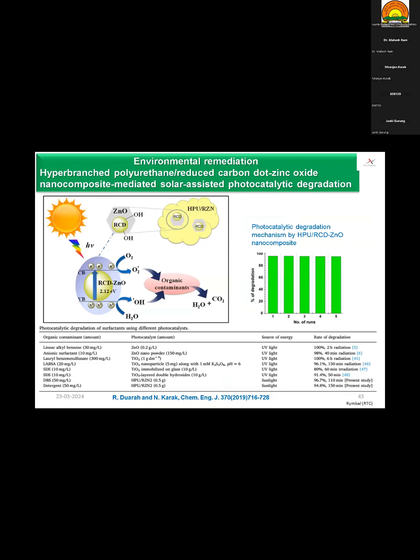Self-cleaning is also possible to obtain through the photocatalytic effect. We have incorporated some nanomaterials here, zinc oxide and reduced carbon dot, in a hyperbranched polyurethane system, and we have seen that this can be utilized to clean the surface. We took different kinds of detergent, and compared to the state of the literature, we have seen that in our system, by using only sunlight, you can achieve 95 to 97% self-cleaning ability of the surface when you apply this kind of nanocomposite system.